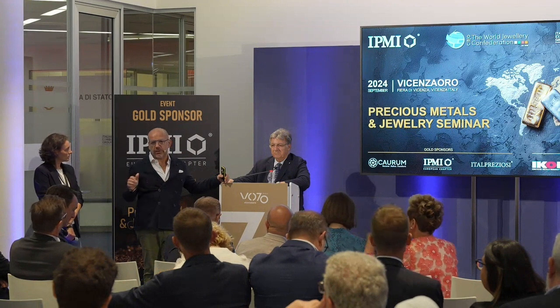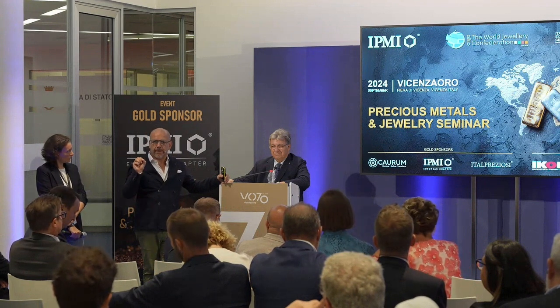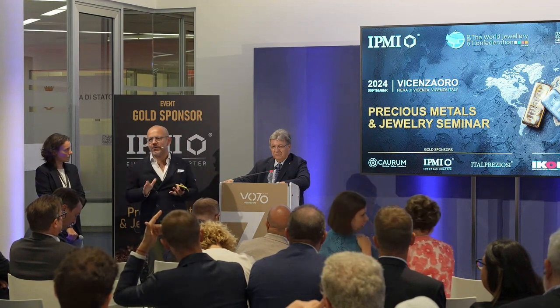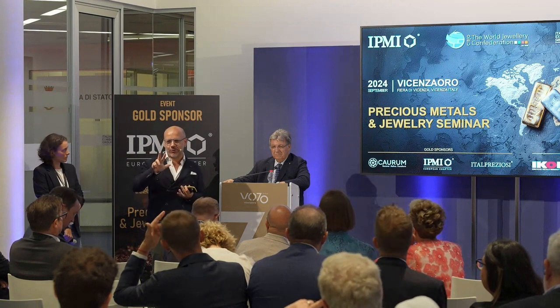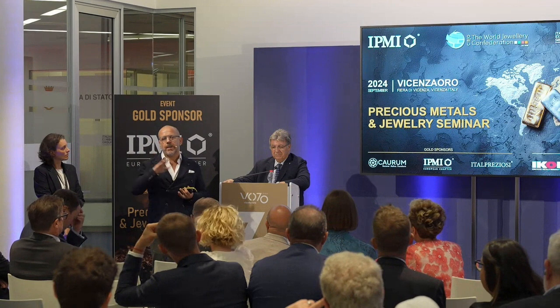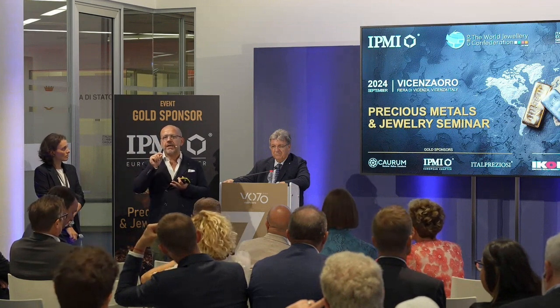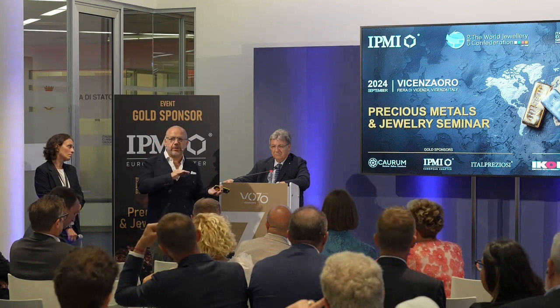Technically, we are working with an Israeli company, so it's mainly there that they do this job, and they go for nanoparticles already on AISI 316L, and it is already in the market. They also do zirconia, but this is maybe more common. But they go for the alloy, not for the single elements. Nanoparticle is a bit of marketing, because finally the D90 of the particles is 3 to 4 microns. But what is very nice is that the layer thickness of every single layer is around 7 to 8 microns, compared to the 30 to 50 microns used in binder jetting or powder bed fusion.